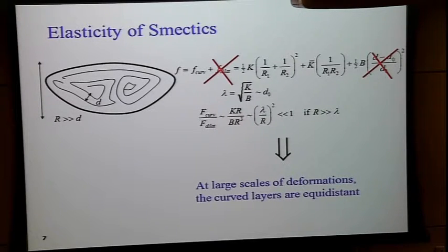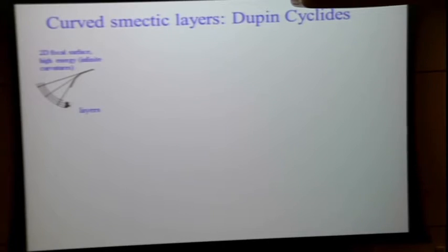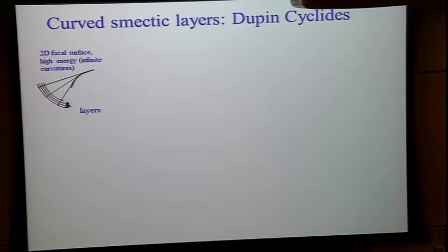It's on the order of lambda over r, which is much smaller than 1 when the size of the system is macroscopic. So you conclude that for large scales, when we have large deformation of layers, the compressibility term can be simply ignored, and you have to first of all think about the curvature deformations of the layers. And this is exactly what leads us to understanding how Georges Friedel found out without X-ray that smectics are what they are. So the reason is purely geometrical.